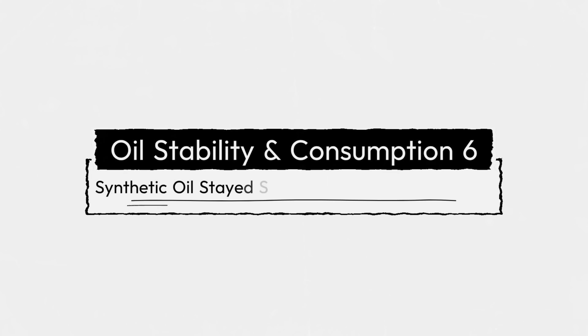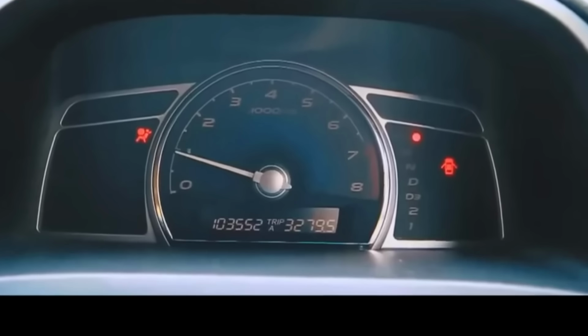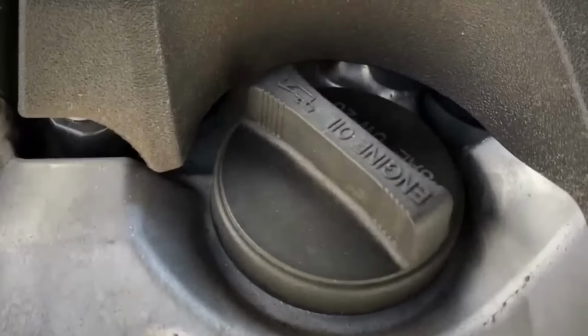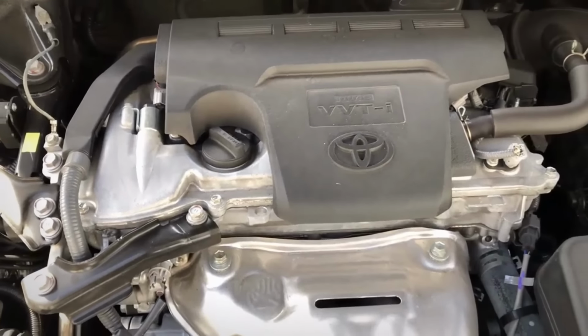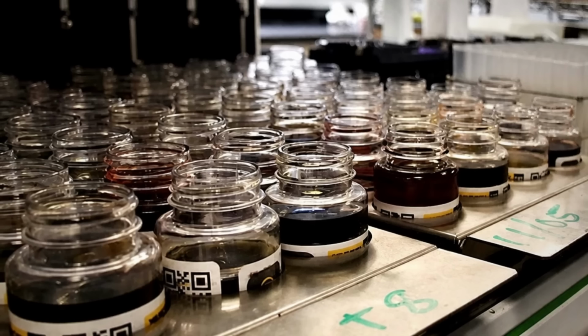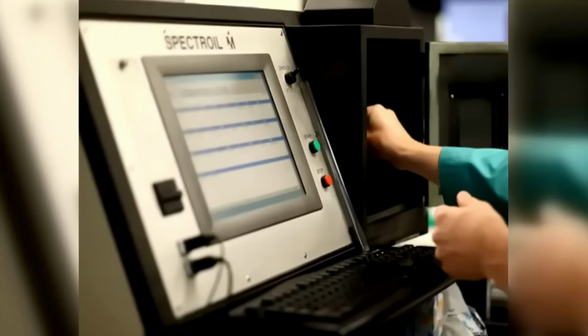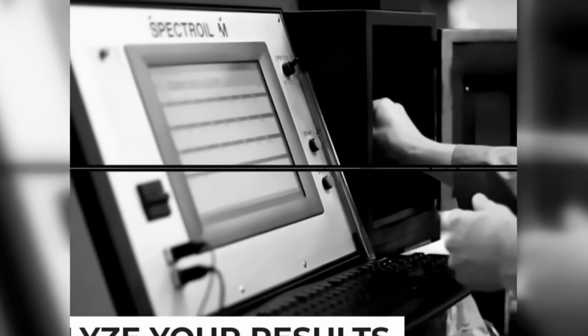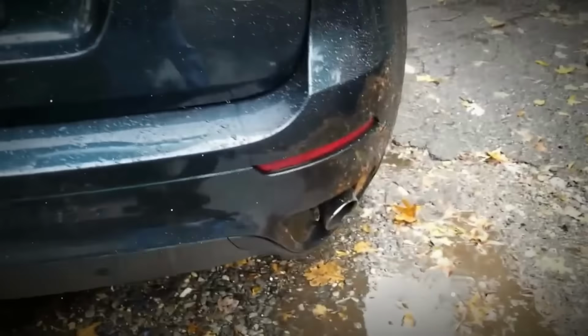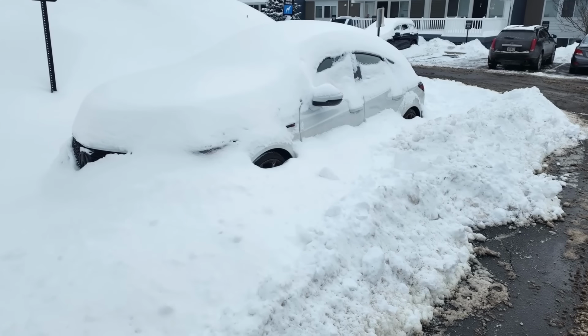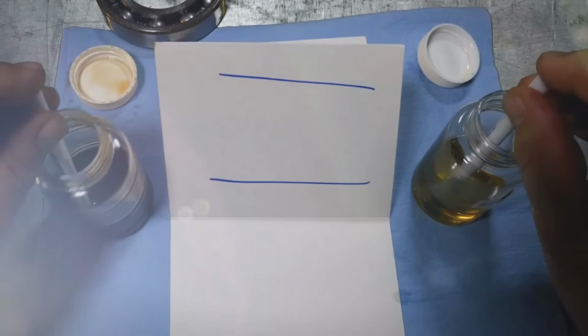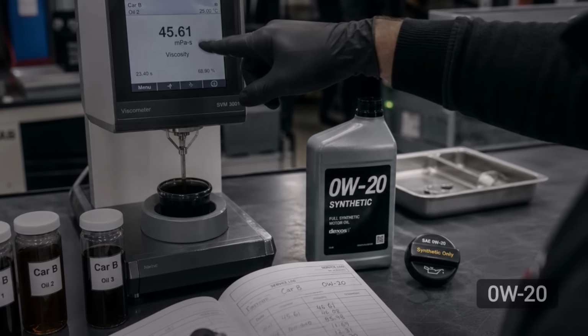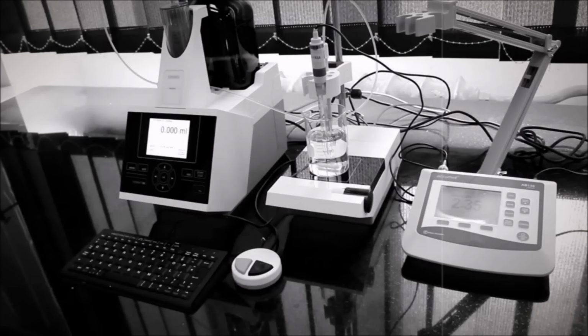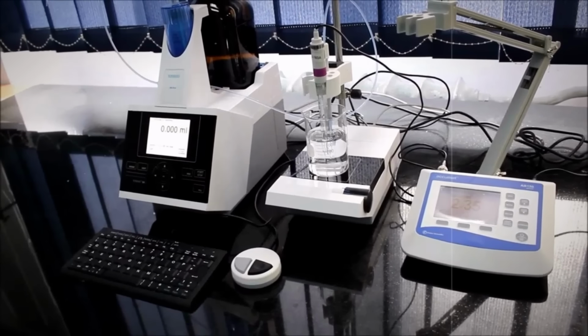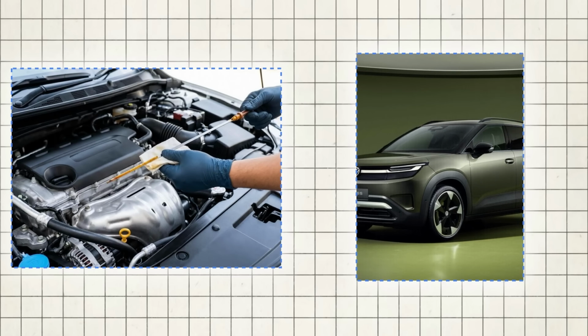Finding number 6, oil consumption and oil condition over the 2-year period, which we tracked at every single interval rather than just at teardown. Car A, running factory fill oil, showed measurably faster viscosity breakdown by the midpoint of each service interval when we sent used oil samples out for analysis. The factory fill blend showed higher levels of oxidation byproducts and slightly more fuel dilution, particularly during the winter months when short trips dominated the driving log. Car B's synthetic oil held its viscosity closer to the rated 0W20 spec even near the end of each interval, and showed lower total acid number readings, meaning the oil was breaking down more slowly and staying chemically stable longer.